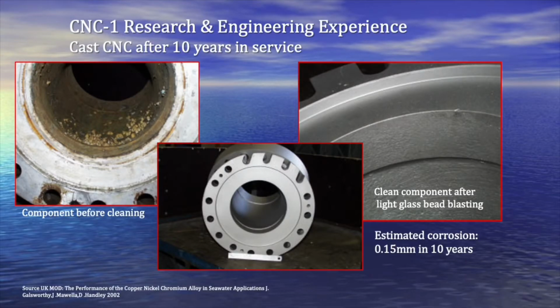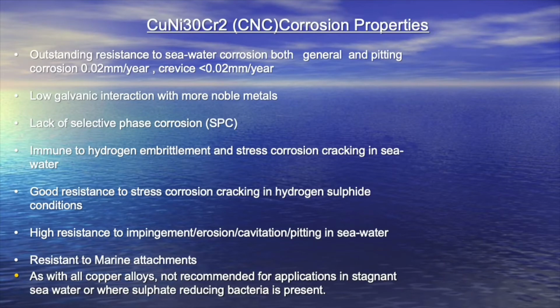This is what a component made out of copper nickel chromium looks like after 10 years of service in a submarine. They took it out of service, they shot blasted it and cleaned it, and they put it back into service because they had identified 0.15 millimeters corrosion in 10 years, which enabled them just to put the component straight back into service without having to purchase a new one, saving time and money and the effect on the environment.